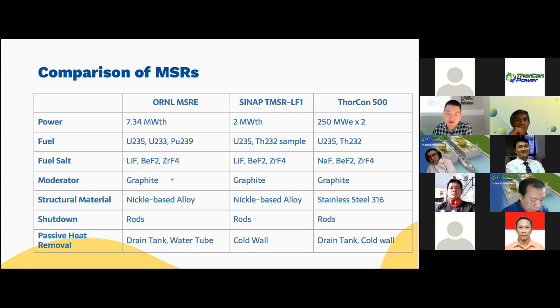And all the concepts I'm mentioning here are using graphite as a moderator. And the ORNL MSRE is using nickel-based alloy, and SINAP again is using nickel-based alloy. While Thorcon is using stainless steel. The reason is that, first of all, nickel-based alloy is an expensive alloy. It's hard to get and hard to manufacture. If you remember, one of the WASH-1222 reports identified that making larger nickel-based alloy components is a challenge for commercializing MSR, but the industry has no difficulty in making large stainless steel components.